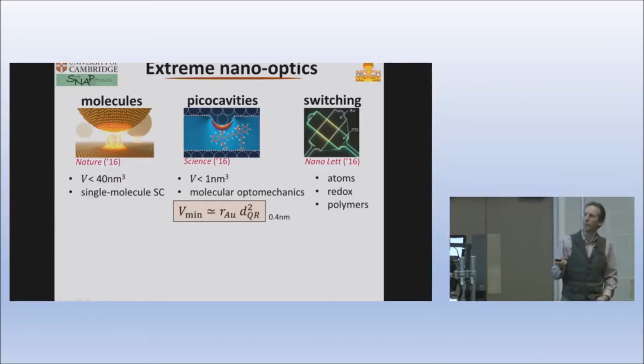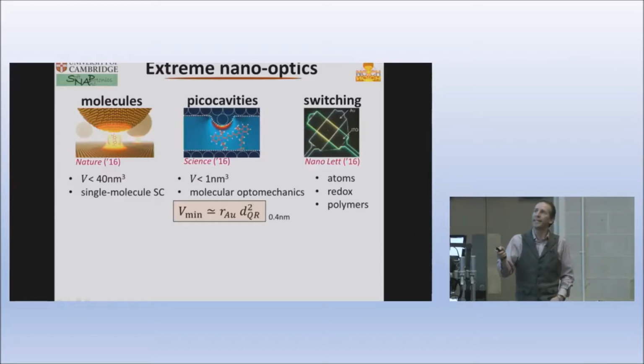Nobody thought that was possible, but now both calculations and our experiments show that indeed when we do that, we actually localize the light there, and we can see it because we look at single molecules when we do that. So we can see Raman spectroscopy. And in fact, what we can do is we can start to make individual bonds here vibrate very, very strongly.